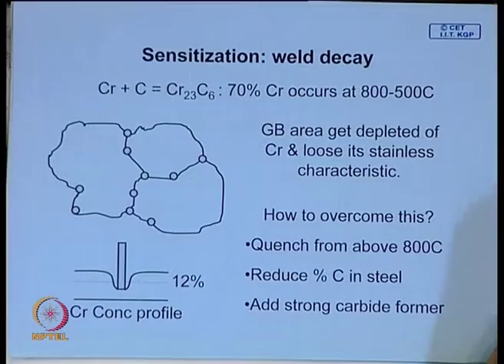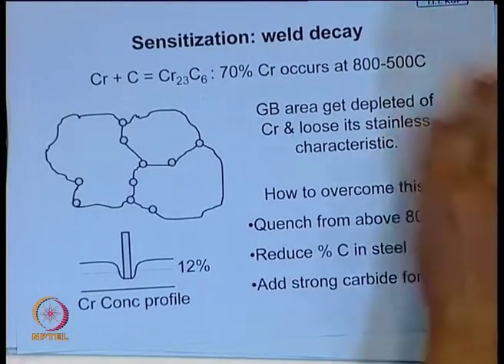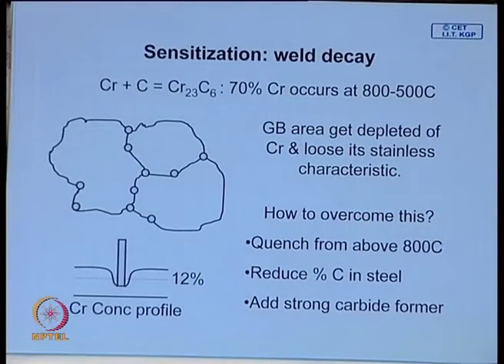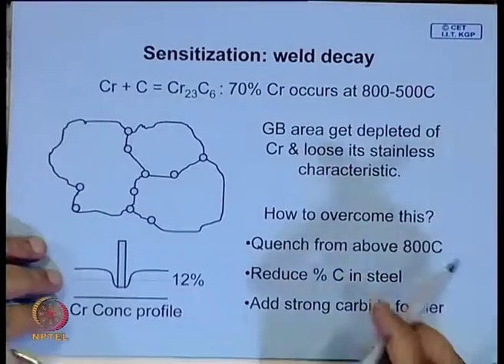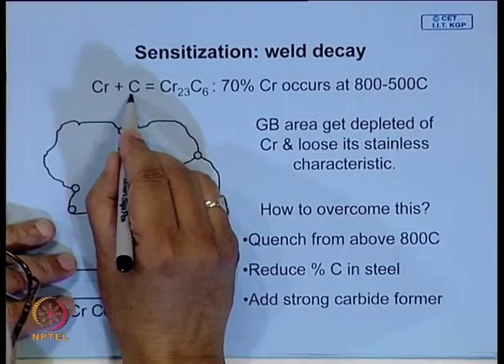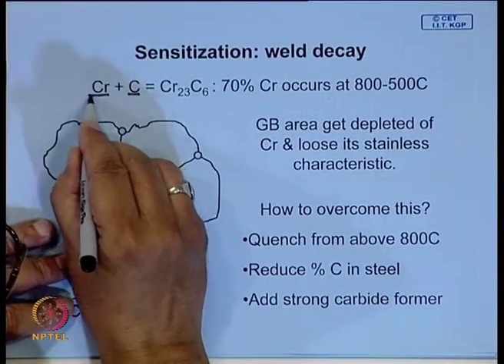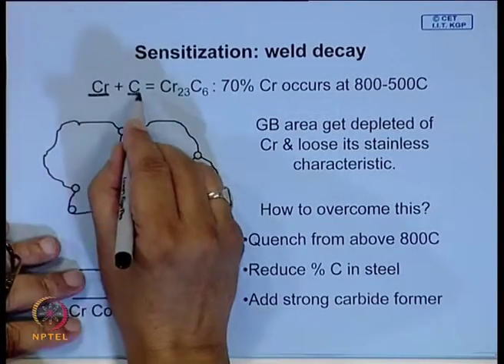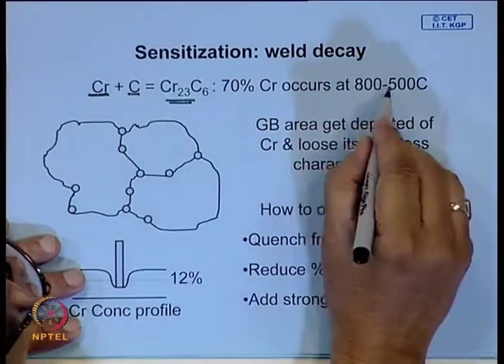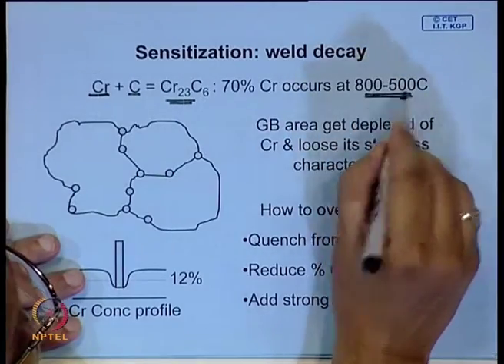Now, let us look at what sensitization is. We mentioned that the oxidation or corrosion resistance of steel is derived from chromium, and only when this chromium is present in solid solution does the steel have good corrosion resistance. No matter whether it is austenitic or ferritic, this chromium must be present in solid solution. Now, the problem is that austenite can dissolve a sufficient amount of carbon as well. So the carbon dissolved in austenite and the chromium also dissolved in austenite may react to form carbide, and this happens if by chance the steel is heated to these regions, which is very common.